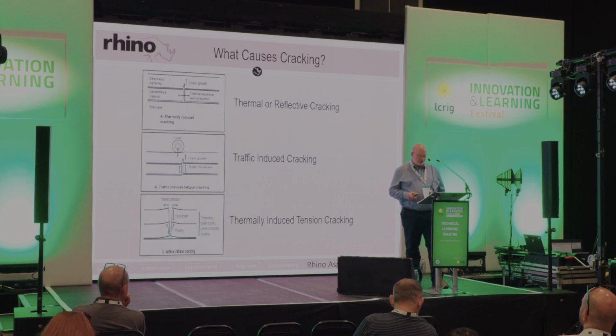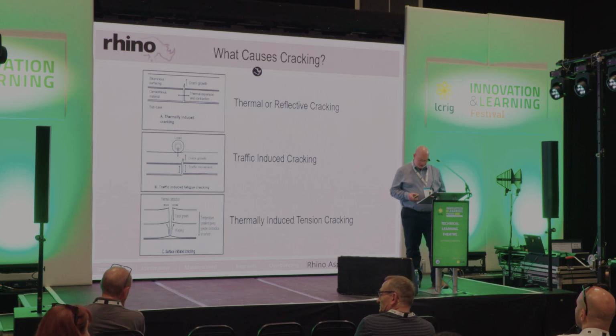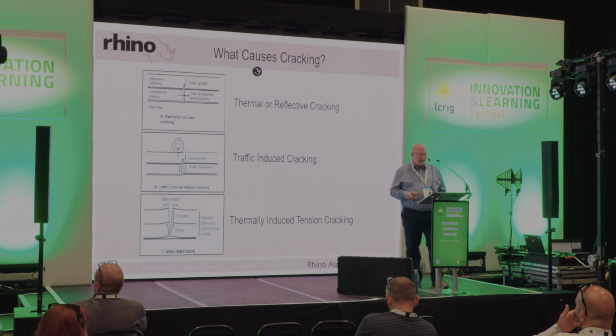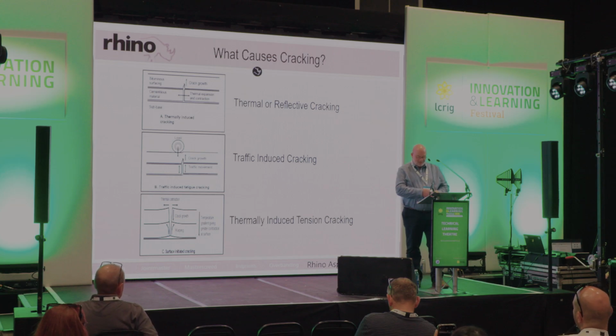Thermally induced or tension cracking occurs when warping stress in the base layers of the asphalt are transmitted through to the upper layer of the surface. Typically, this is most likely in spring and autumn, where there's rapid changes in temperature. In this instance, cracking will typically occur at the top of the asphalt layer and work its way downwards.